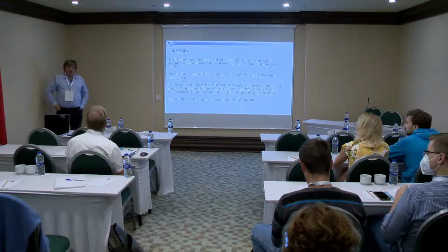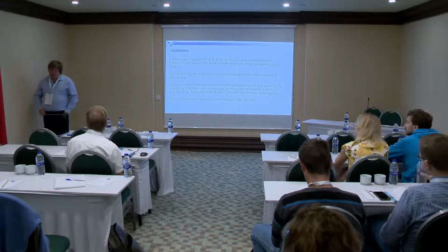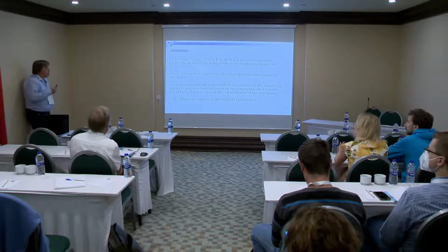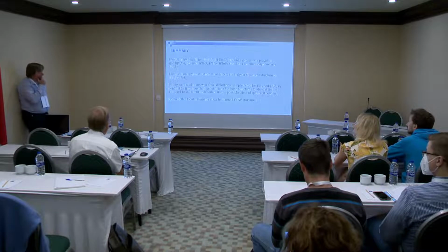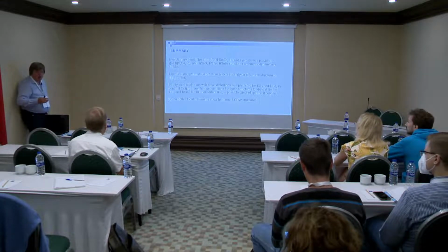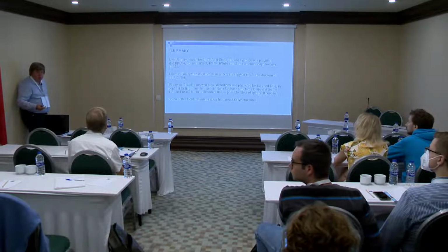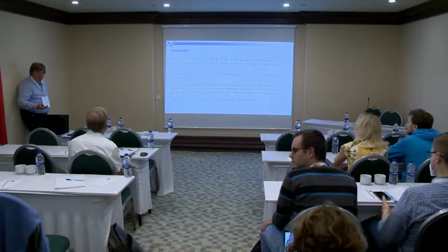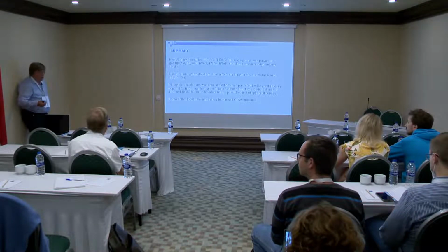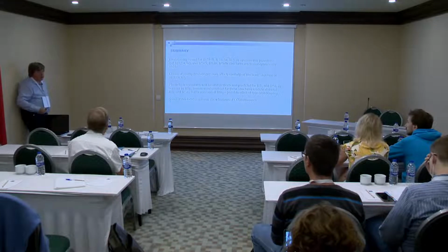No, we do not see any role. That is surprising. So basically, if I compare titanium disulfide and titanium diselenide, there's almost no difference. I have, for both of them, a lot of metastable states. There is already a big difference between sulfur and selenium, but we do not see it here.